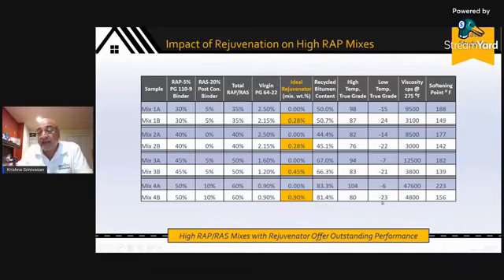You can see the impact of performance, no rejuvenator versus rejuvenator case. Dramatic improvement in low temperature, fatigue tolerance, thermal resistance, etc. Absolutely stupendous effect on viscosity. This is a material at 48,000 centipoise. It cannot be processed. You cannot put it down on a roadway. At 4,800, you're approaching polymer modified bitumen levels, a little bit stiff, but still can be laid down. And you can see the dramatic influence that has on your softening point and your penetration.